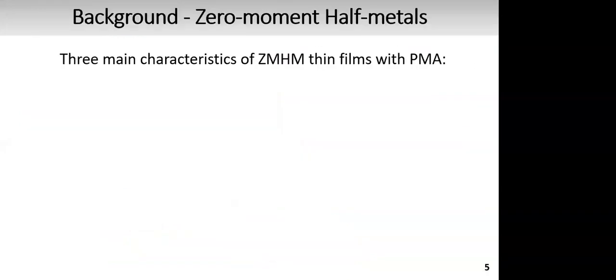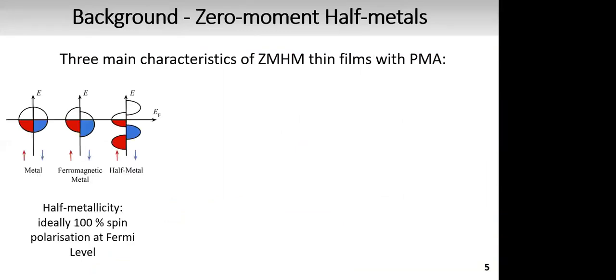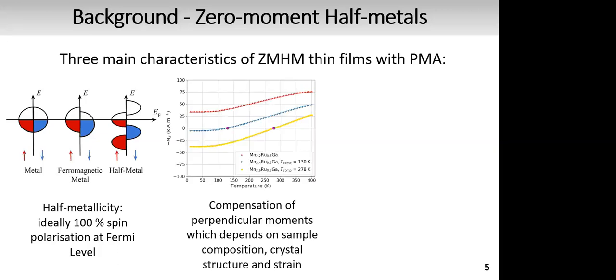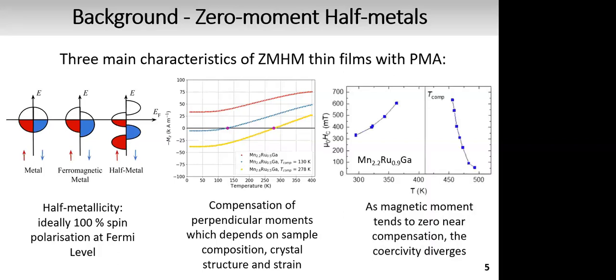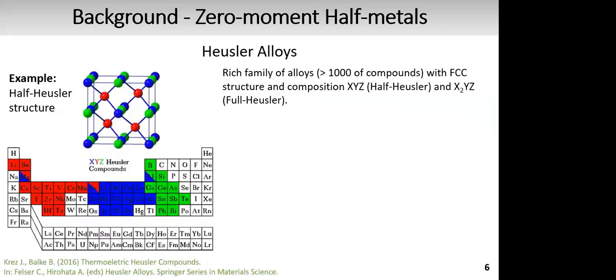So there are three main characteristics of zero-moment half-metal thin films with perpendicular magnetic anisotropy. The first one is half-metallicity, which gives you an ideal 100% spin polarization at Fermi level. Secondly, we have the existence of a compensation point at a particular temperature. And last but not least, we see that the coercivity of the material tends to infinity as the net moment tends to zero, closer and closer to compensation. So as I mentioned, the first zero-moment half-metal that was discovered is a member of the Heusler alloy family. So I want to talk a little bit about Heusler alloys.